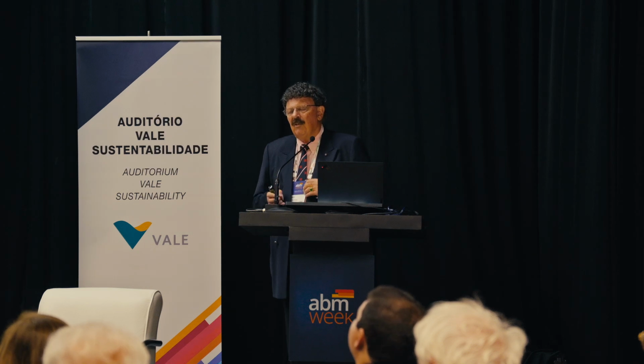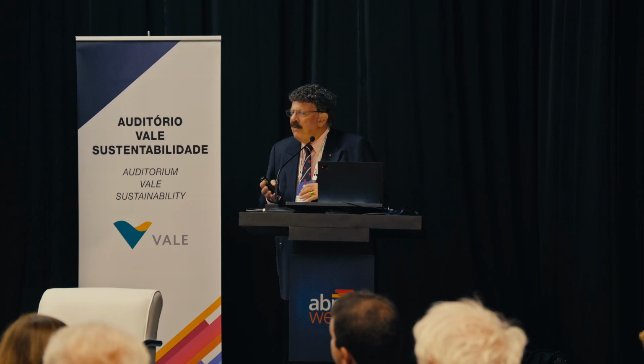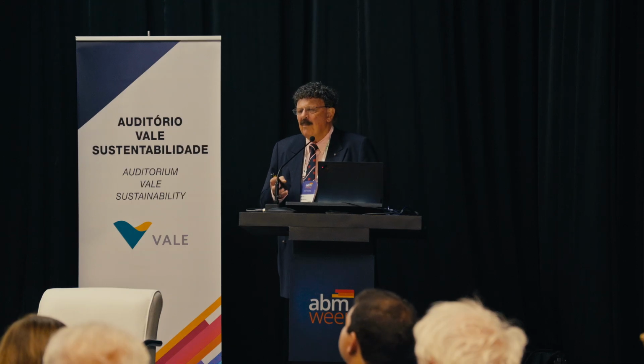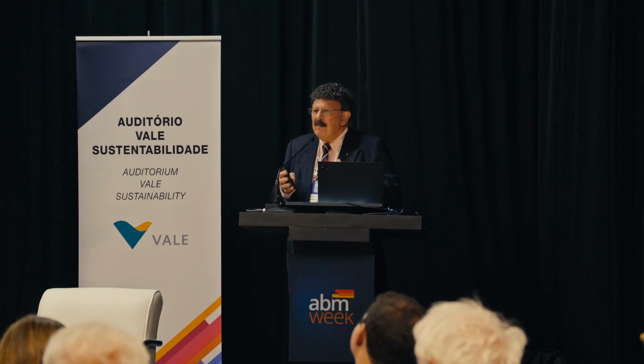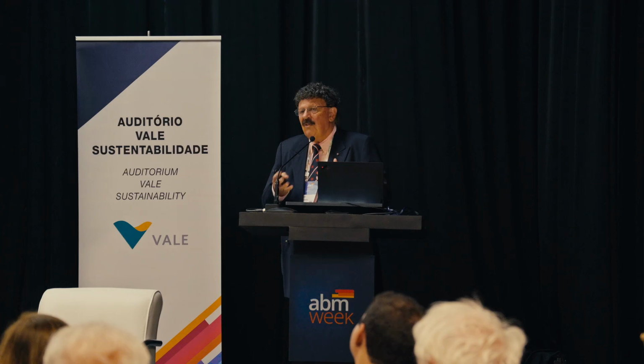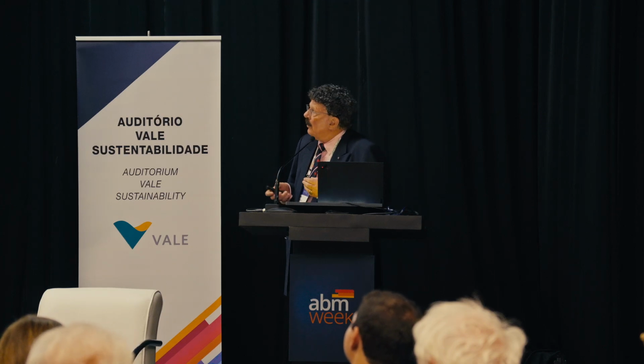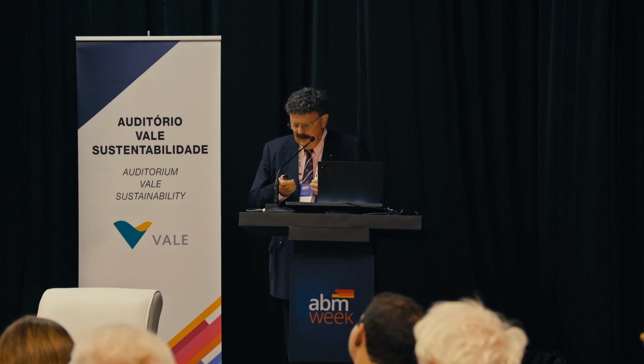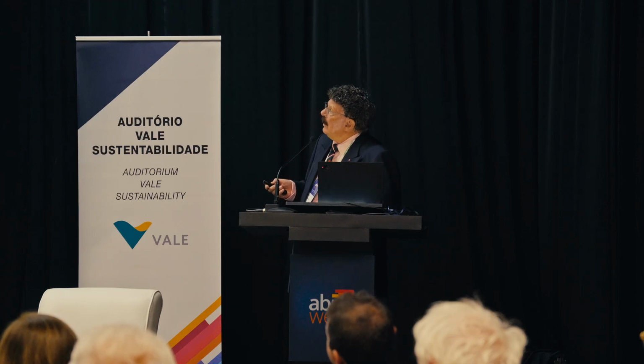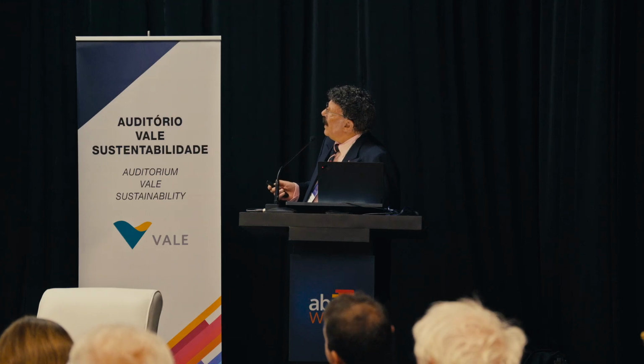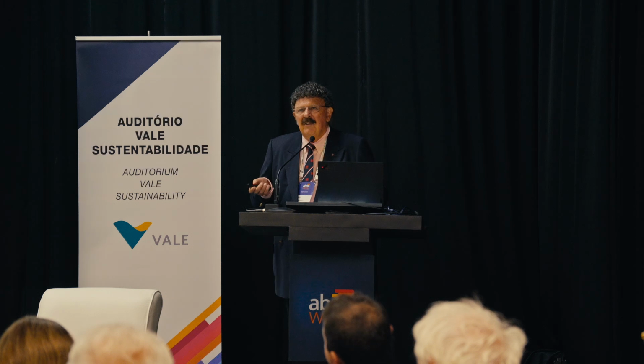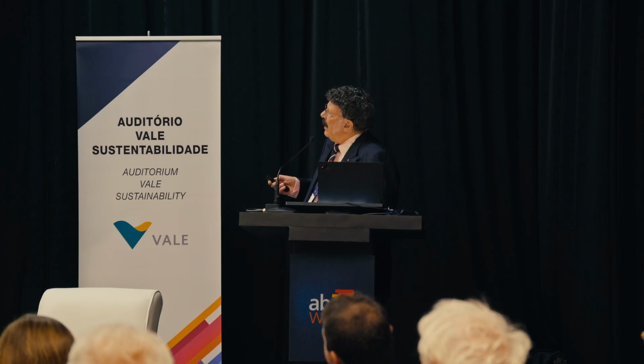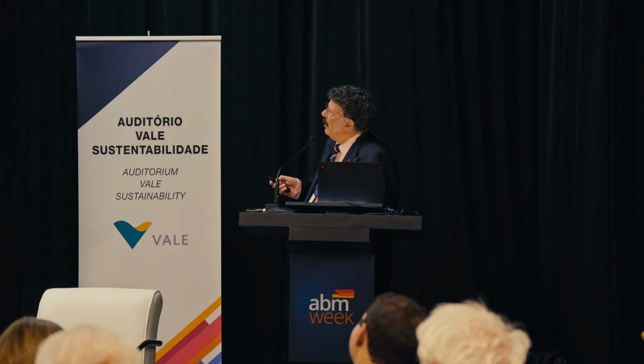I won't talk too much about this, but we've also looked at additive manufactured versions of these materials. Additive manufacturing is very interesting. It can cause real problems in generating defects and voids, but you can generate structures that you can't generate any other way. And these are still basically nominally single-phase structures, but by using laser powder bed fusion, we can generate this sort of hexagonal type structure which has a B2 phase, which is like the coherent phase in a nickel-based superalloy, in a honeycomb type structure. So basically,